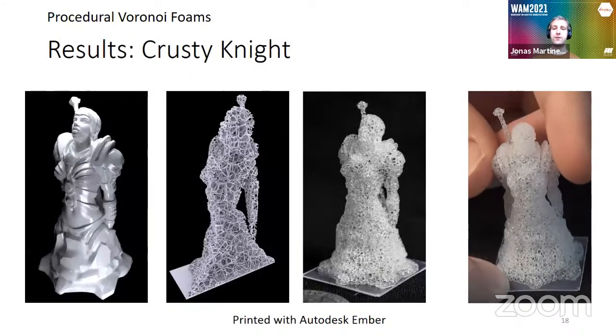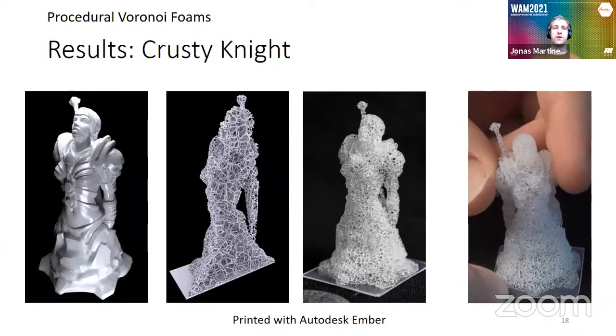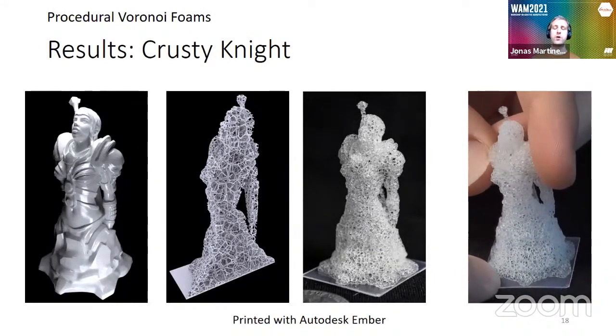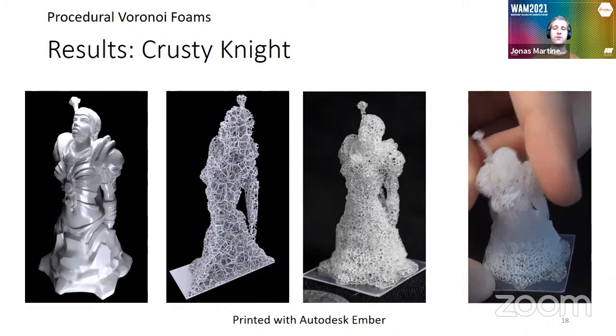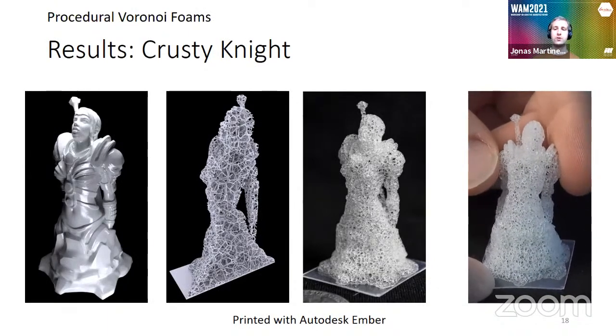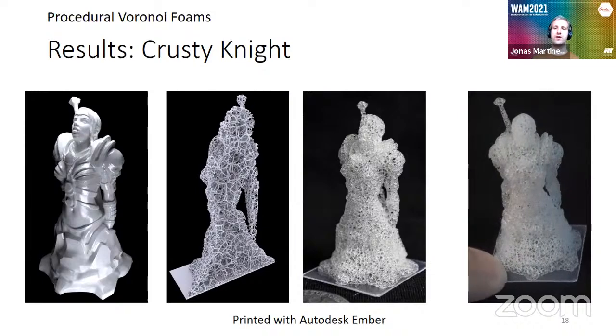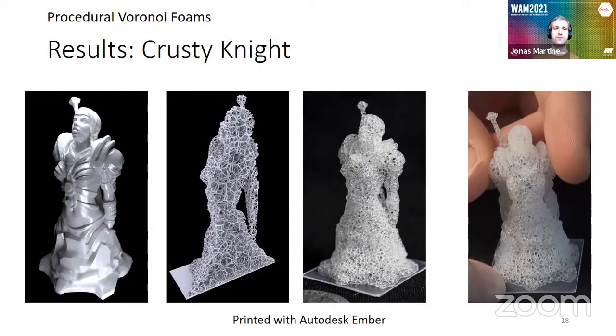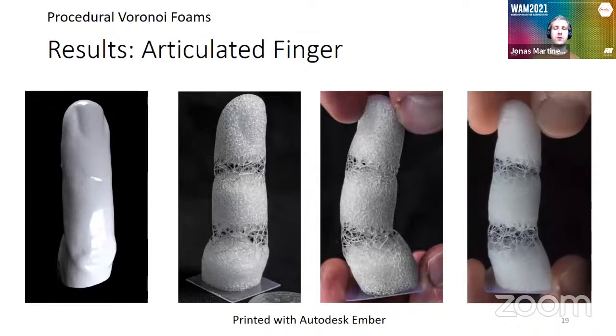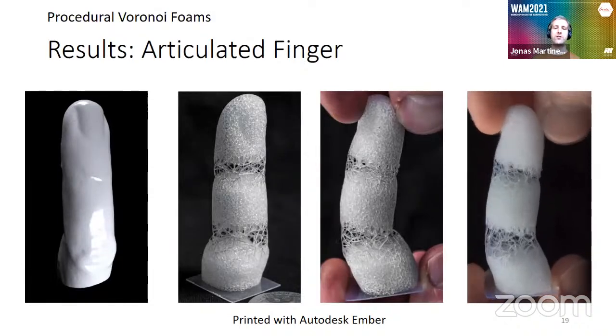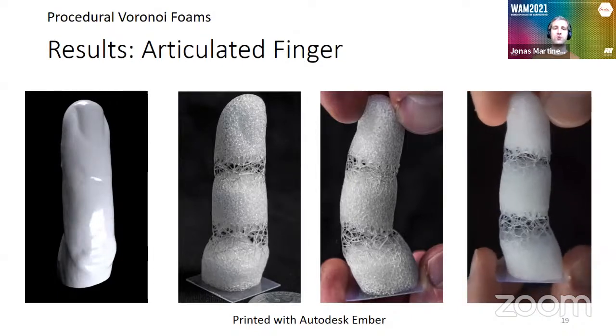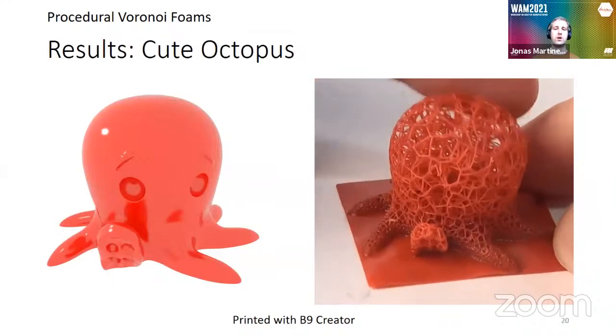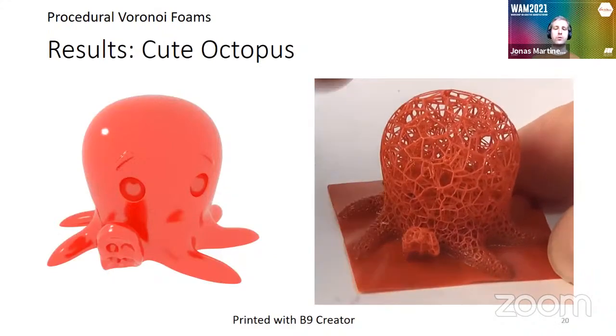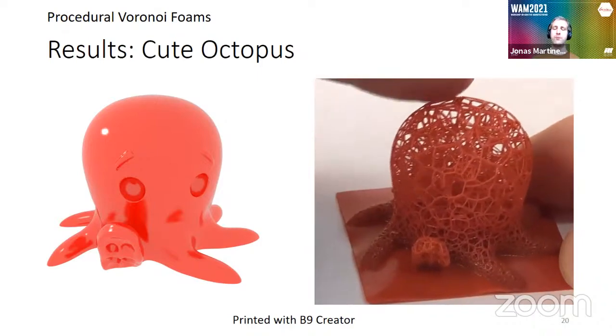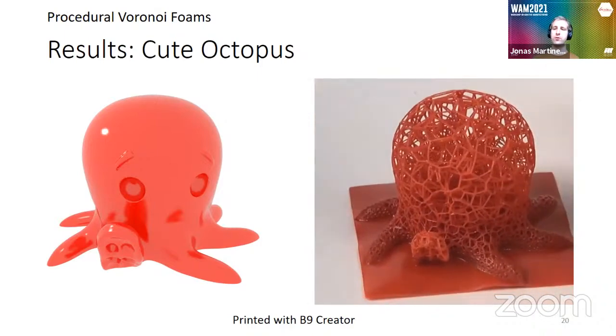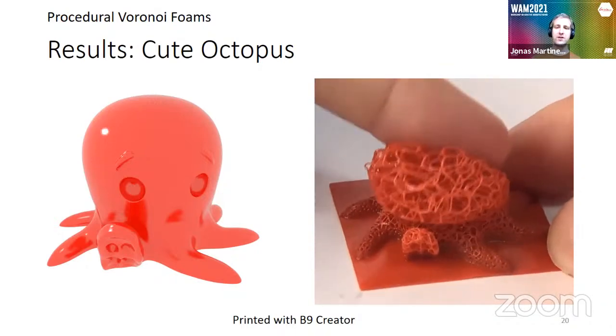So here you can have a glimpse also of some of the results we did. These were printed with an Autodesk Ember, which unfortunately is not available anymore. So you can see that we were able to print very low scale structures. Here you have another illustration, an articulated finger, where we basically are playing with the density on the articulations. Here we have our cute octopus. This was printed with B9 Creator. Up to the date, we're still torturing this octopus and it's still resisting, so not bad for him.